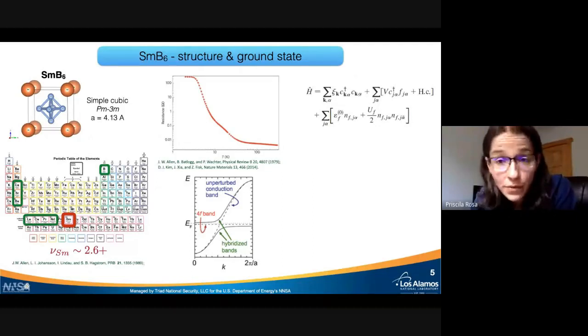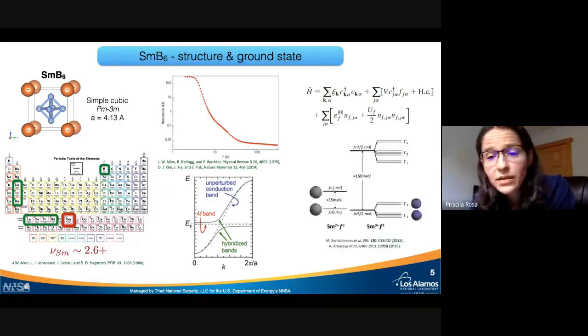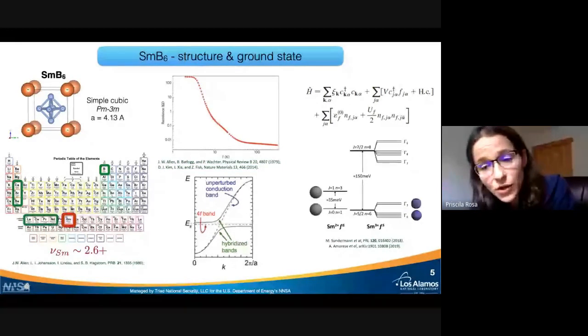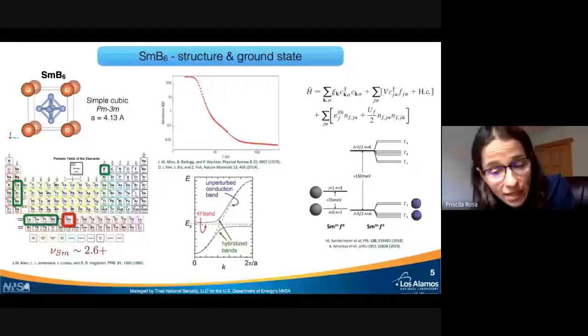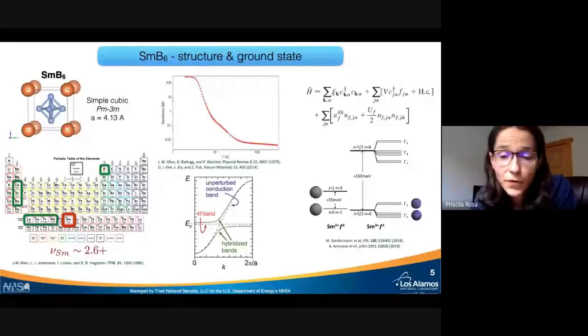So here is the Hamiltonian for that. We have conduction electrons, and then we have a hybridization term, V, between conduction electrons and F electrons. And then we have an on-site Coulomb interaction, U, in the F electron site. So we know very well what's happening at high temperatures and the formation of the gap. Very recently, actually, there are also some measurements of inelastic X-ray scattering showing that the ground state of this material is a gamma-8 state, which is a very nice piece of information.